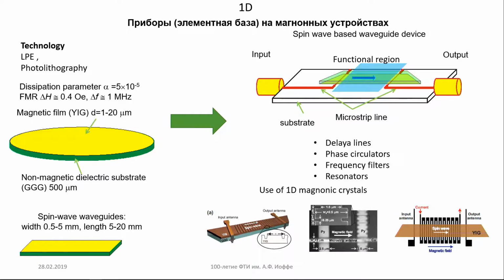excites the magnetic structure. And this excitation is excitation of magnetic moment, therefore spin wave can start to propagate. And its frequency depends on the excitation frequency of electromagnetic current, which is AC current, which is in this input microstrip transducer. The propagating spin wave goes down to the output microstrip, again excites current, and therefore by spectroscopy you can measure the propagating signal. Depending on the wavelengths, the delay time of propagating signal compared to electromagnetic wave propagating in this material, which is not related to the electromagnetic wave, the delay can be in microseconds, nanoseconds, depending on the frequency.